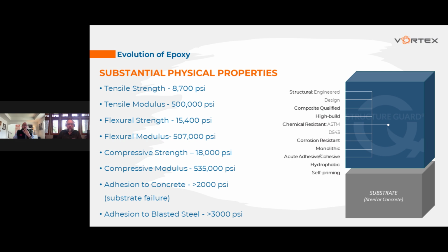Great. So if you're using a concrete underlayment, how long is the typical cure time before the epoxy coating can be applied? Yeah, so there's different types of underlayments, and you've got underlayments from Quadex, from Vortex Companies, Quadex Repair Materials. Hyperform is an underlayment that can be used, and after Hyperform is installed, you need to wait an hour prior to installation. 2 hours is probably best practice.